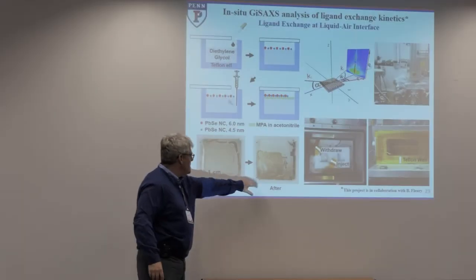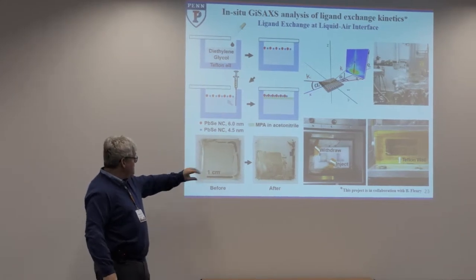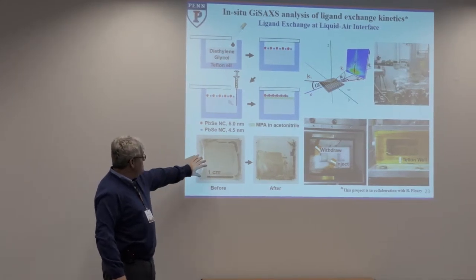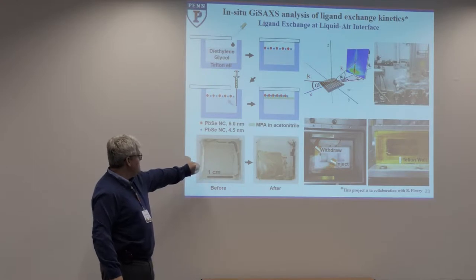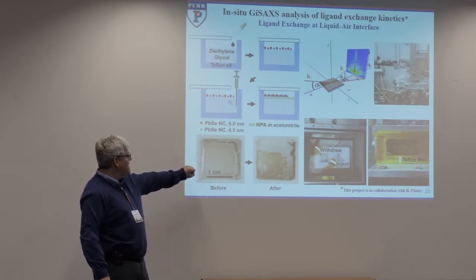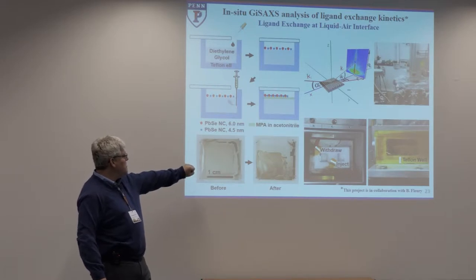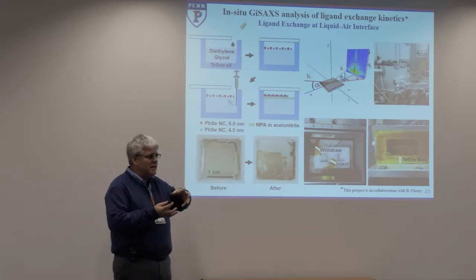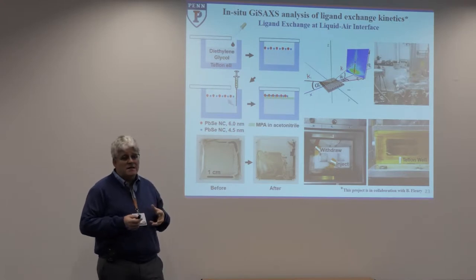Why would we go to that trouble? Well, it turns out that this exchange process is still one of the more challenging steps in getting the properties that you want, because of something you might be able to pick out in this image here. As you do the ligand exchange to bring the particles closer together and get this strong electronic coupling, you're fighting against a strong force that is contracting the overall structure. And those stresses lead to the development of defects, cracking, and other things that are really a problem in terms of reliability when you're doing fabrication.